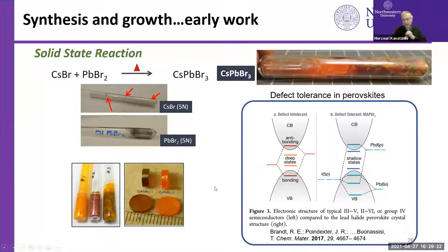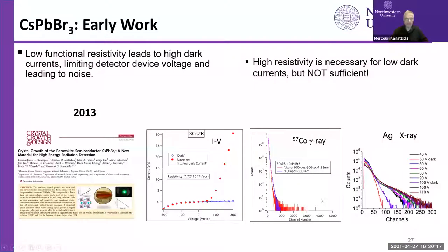So why is the perovskite defect tolerant? That's because, unlike a conventional semiconductor like gallium arsenide or cadmium telluride, which when it has defects like vacancies and other things, it creates deep level states in the gap, which act as traps and kill the signal. This material, when it has the same kinds of defects, doesn't create deep level states. Either they are shallow, very close to the band edges, which is good, they're not as harmful in that case, or they go well inside the band, in which case they're not affecting charge transport. So this is one of the reasons that they are defect tolerant.